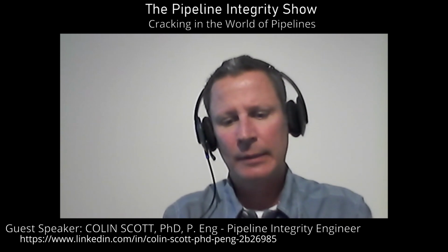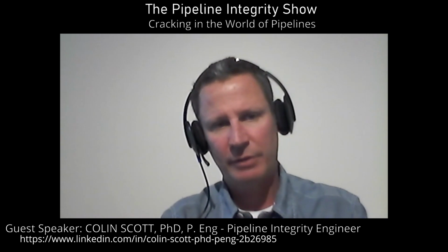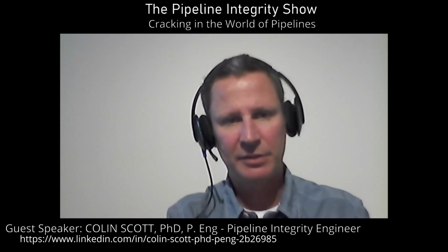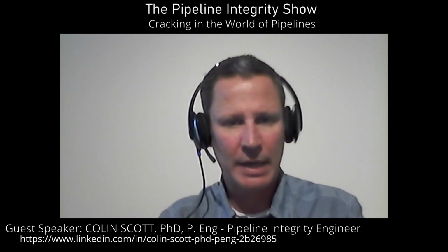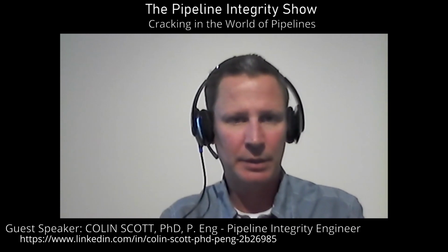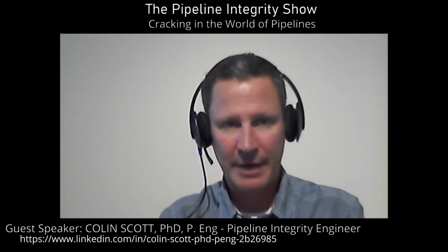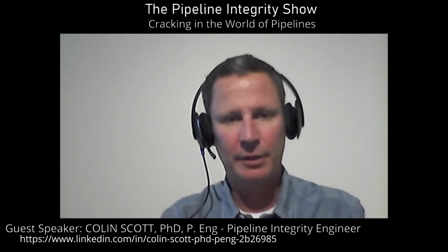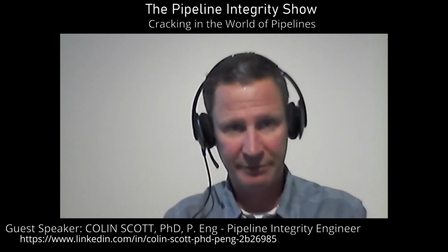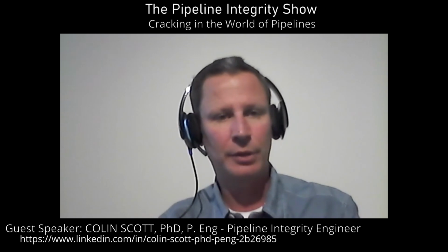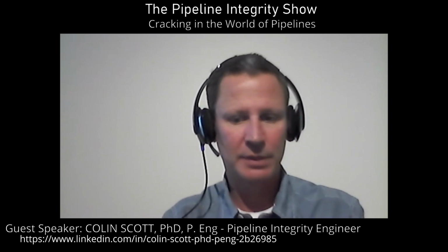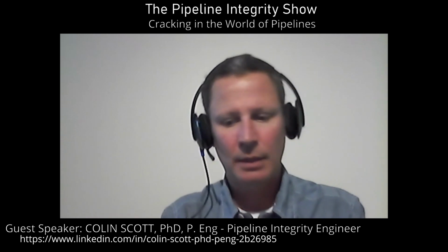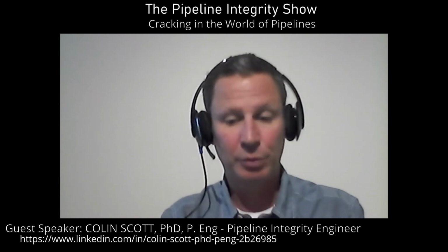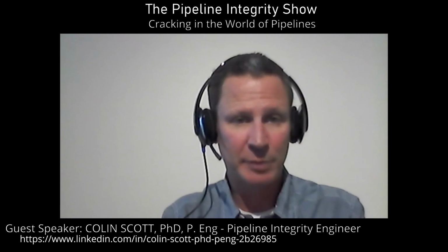With this, rather than the log secant models where you have elastic plastic behavior buried into the same math, with the failure assessment diagrams you're actually doing two separate calculations. One is a brittle fracture calculation, where you're comparing your stress intensity factors to a toughness. The other is you're looking at ductile failure or plastic collapse. You do these two calculations independently, and you plot your results on a failure assessment diagram.